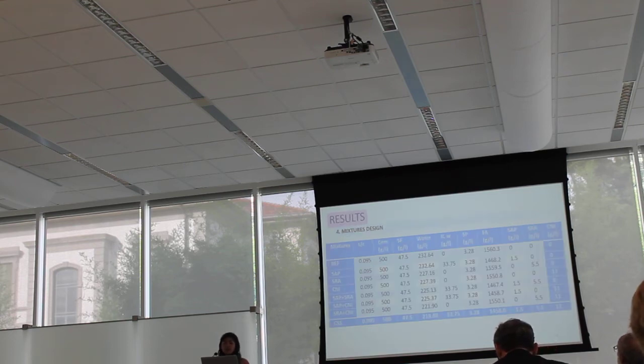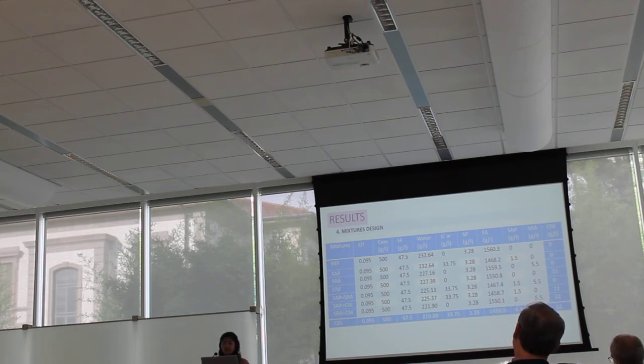This is the mixture design of all the mixtures. We have a reference with no admixtures, then a reference with the SAP, then with the shrinkage reduction admixture, then with the calcium nitrate inhibitor, and then a combination of all the admixtures, to know the influence of all these on the autogenous shrinkage measurements.